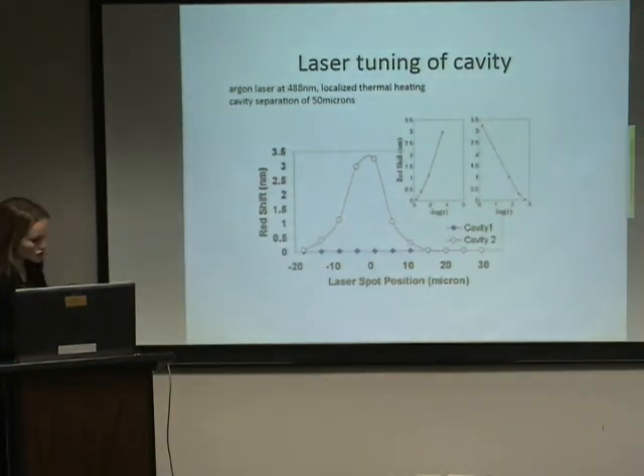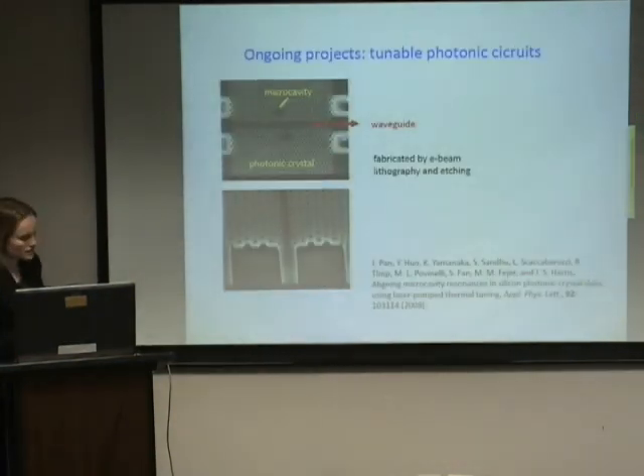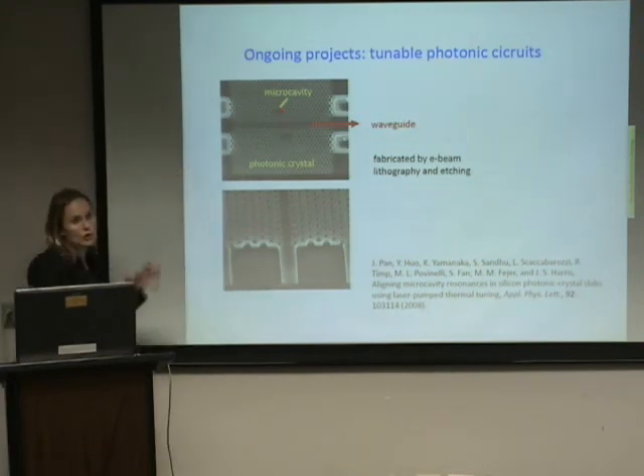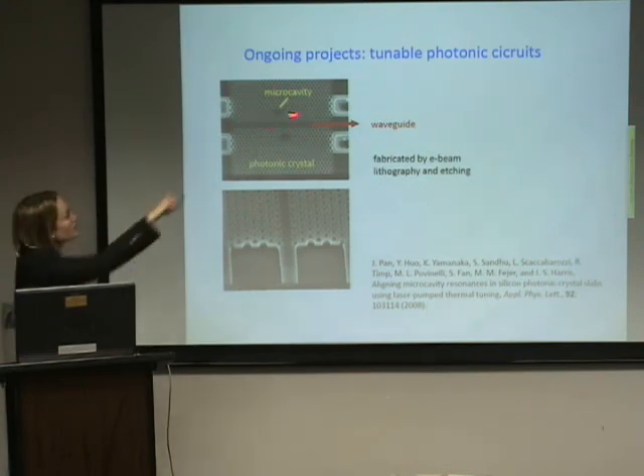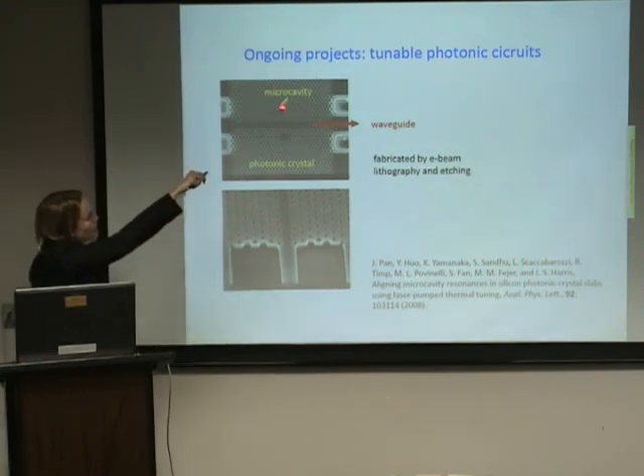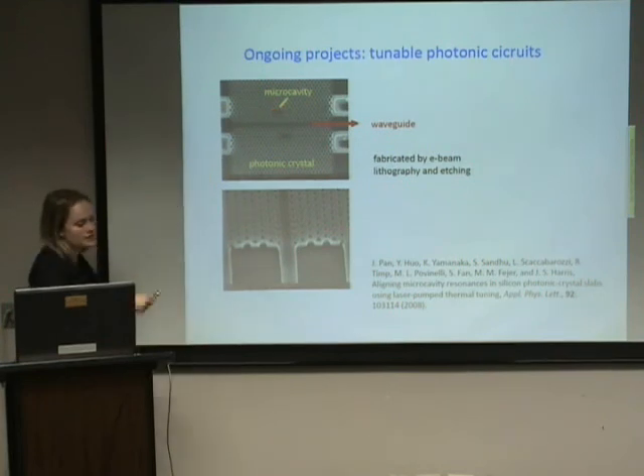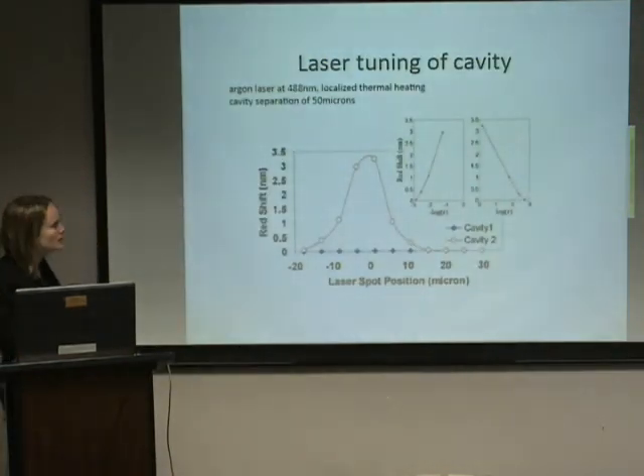And we were able to show that one way of tuning this structure is that you take a laser and aim it right at a microcavity. Locally, the cavity looks different. So if you remember way back to the beginning of this talk, we said any kind of local change to a resonator shifts the resonance. This is one example. You shine light, you get a lot of free carriers right nearby, the index changes and things shift. So we were able to use a laser to shift our resonance around. We move the laser spot, and we see a shift in the resonance of a few nanometers.